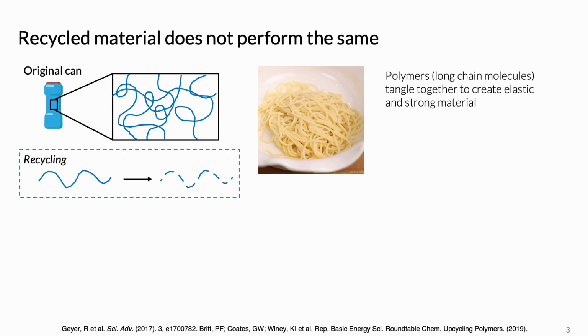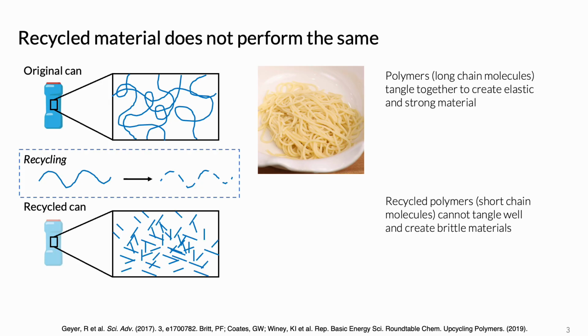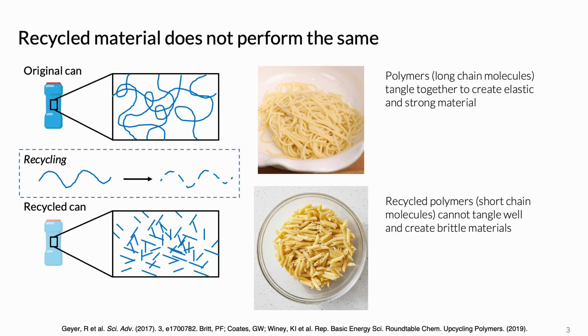And when plastic is recycled, it gets chopped up, and so do these polymers. These chopped up strands are then used to form a recycled can, but now because it has much shorter chains, the tangling doesn't happen, like in this bowl of cooked short pasta. If you pick up one piece, nothing comes along with it, and you're able to separate it out easily. This results in a plastic that is brittle and weak, and to combat this, manufacturers will add back in more of the pure long-chain polymers, creating essentially new plastic.